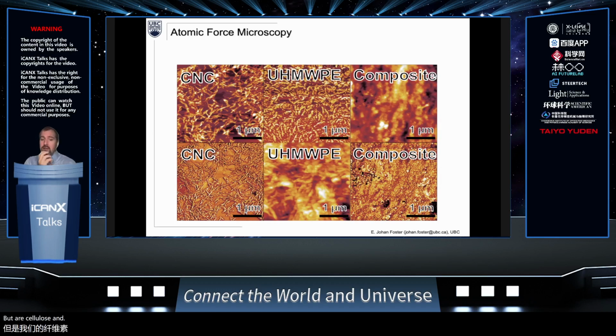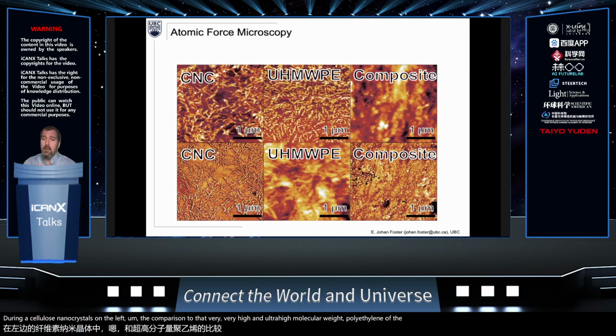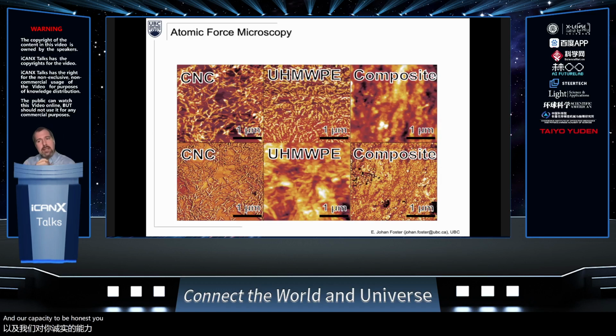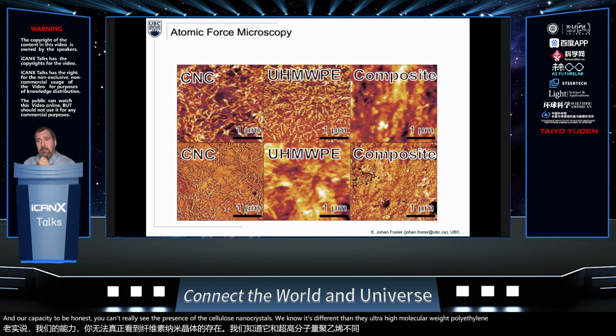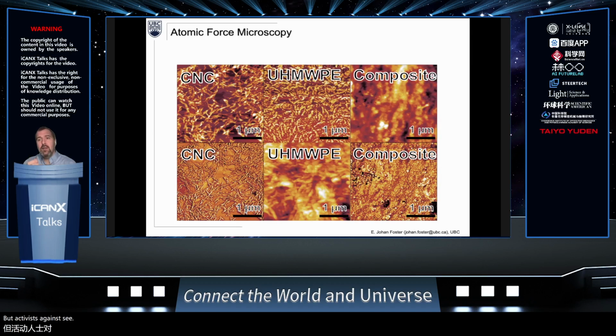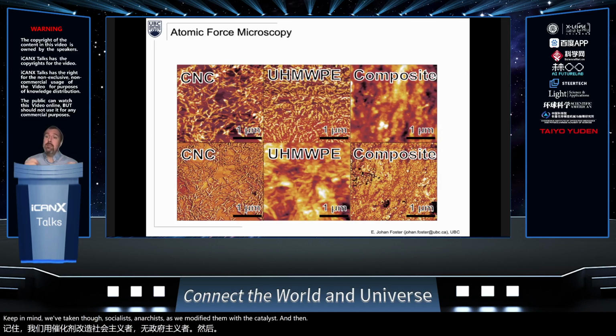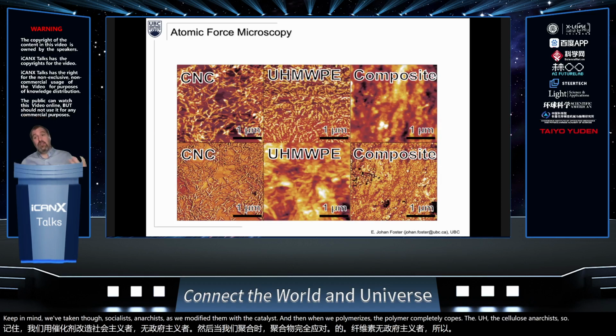But our cellulose nanocrystals, so this is AFM, atomic force microscopy, showing our cellulose nanocrystals on the left. The comparison to that very high-end, ultra-high molecular weight polyethylene in the center and our composite. To be honest, you can't really see the presence of the cellulose nanocrystals. We know it's different than the ultra-high molecular weight polyethylene, but to actually see the presence of those is very difficult. In this case, keep in mind, we've taken those cellulose nanocrystals, we modified them with the catalyst, and then when we polymerize it, the polymer completely coats the cellulose nanocrystals. So that's good in the case of the composite, but very difficult in actually the imaging.